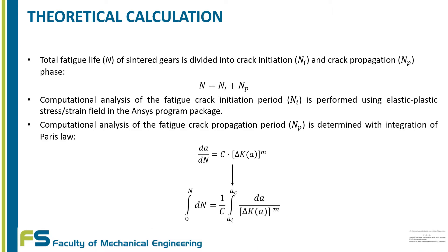Total fatigue life is divided into crack initiation and crack propagation as shown in the first equation. Computational analysis of the fatigue-crack initiation period is performed using an elastoplastic stress-strain field in the ANSYS program package with the strain-life approach. Computational analysis of the fatigue-crack propagation period is determined by integration of the Paris law as shown in the equations below.